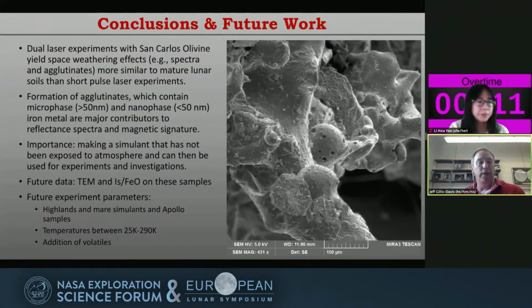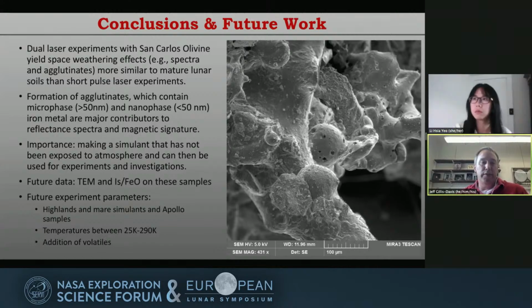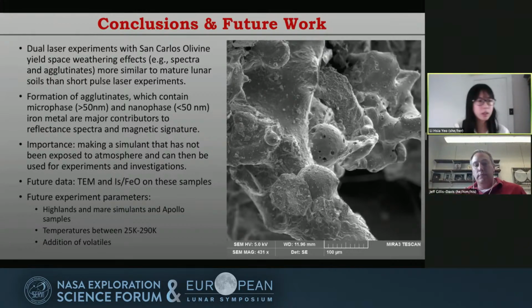And then for our conclusions, with the dual laser experiments and only using San Carlos olivine, we are pretty well reproducing things. We're able to form agglutinates, and the big takeaway is that once we create these under vacuum, we can do other experiments. We're still waiting to get some TEM and I sub S over FeO values for these materials. Thank you.